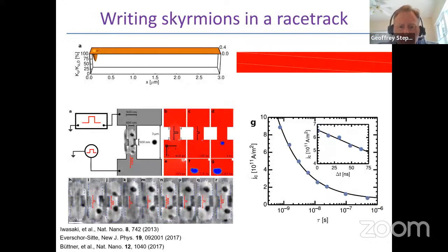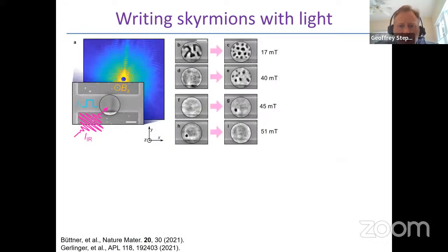Magnetic skyrmions can be written in racetrack devices. This has been shown by our group and in a number of other groups, both with simulations and with experimental work. I won't go through the details of this as of yet, but using ferromagnetic multilayers based on a ferromagnet sandwiched between two dissimilar metals or a metal and an oxide, many of the requisite functionalities, at least in principle for a device, have been demonstrated. And even phenomena like ultra-fast generation of magnetic skyrmions.